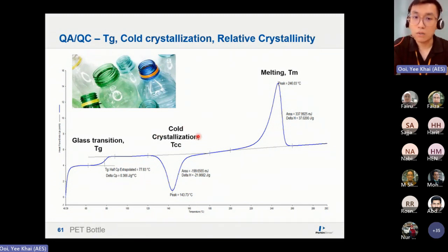If I don't want to see this, what I can do is heat up fast. But of course, like I mentioned just now, this depends on how fast your instrument can heat without losing control. Always remember, it is under a controlled state. With a DSC 8000, we can heat up to, for example, 300 degrees C per minute. Then it's going to suppress the crystallization and go straight to melting. So for very, very fast heating, you wouldn't see crystallization anymore.